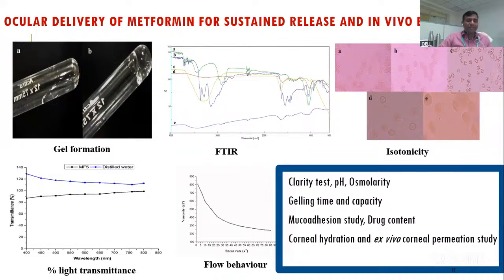This figure indicates that the formulation is liquid at room temperature and gels at physiological conditions. The polymers and the drug that we have taken here are compatible with each other. And further, to know the biocompatibility, we have performed isotonicity testing using RBCs.